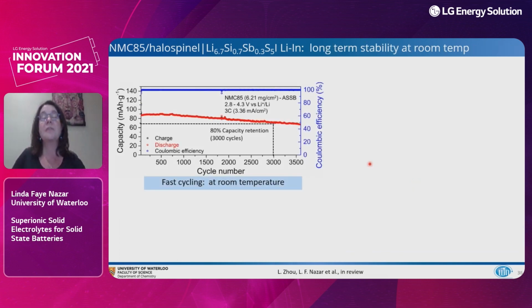So what this gives is a cell that really functions pretty well. This is at room temperature, and this is at a 3C rate, because we've also done studies at 2C. This was our initial study because we wanted to get the data collected quickly. So you can see that we achieve 80% capacity retention over 3,000 cycles for this cell. And again, I repeat, this is at room temperature.